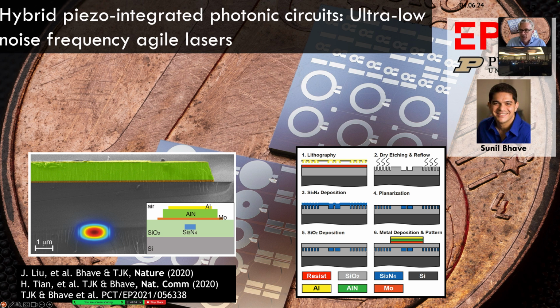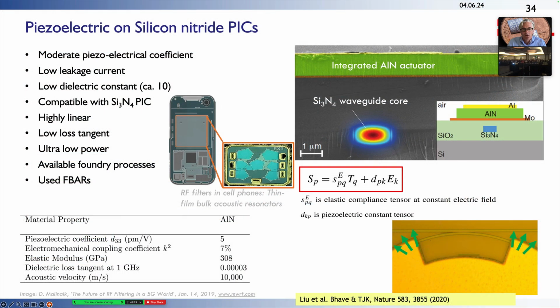And I'd like to briefly explain what the rationale is and also what new applications this can allow. So first of all, very briefly, I don't have to be too detailed here for this audience. The material that we have focused on in our initial work is aluminum nitride. And what is very unique about aluminum nitride? It's a material that's extremely commercial, has low RF loss tangent. It provides highly linear actuation with very little hysteresis. It's very low power. It has a low dielectric constant, which compensates for some of the lower piezoelectric coefficient, and also has a low leakage current.